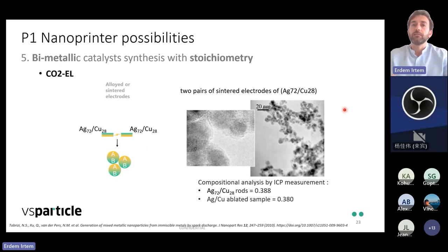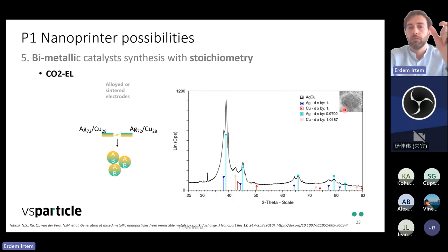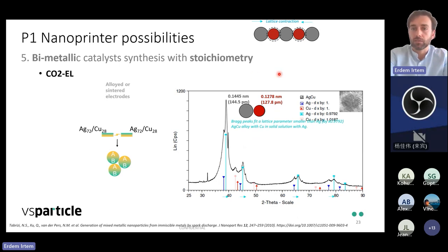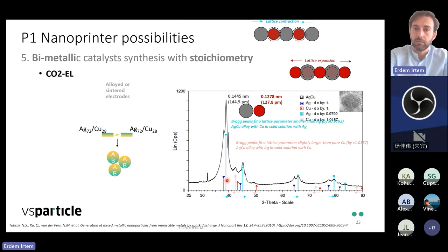And there is, in fact, a silver copper publication which has been conducted with ablation technology, with similar machines to what we have in the lab, and they were able to show that silver copper could be mixed at a higher ratio than the conventional method. They just have a pre-alloyed copper silver, but after the ablation the mixing ratio was much more uniform. They checked the XRD, and they talk about something quite interesting, which I also linked with CO2 electrolysis. They mentioned that silver has 144 picometer diameter and copper has 127. When they look at the peaks of the silver, there was a lattice contraction according to the peak shifts and appearance of new peaks. And then there is a lattice expansion for the copper, appearance of new peaks and the Bragg peak shifting.